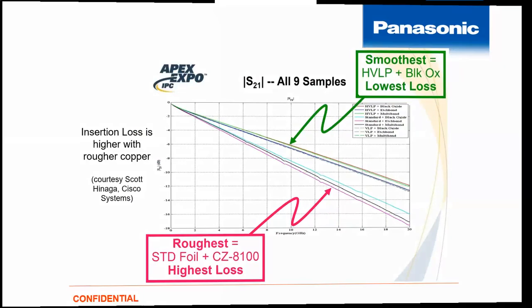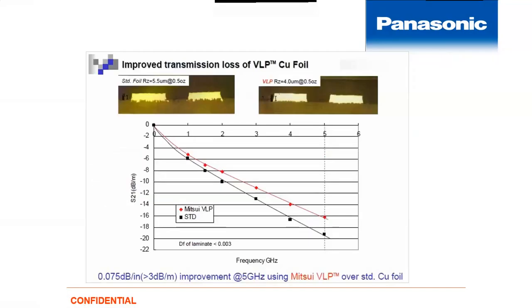If we look at just a comparison between standard foils and VLP, you get the point here again. The VLP performs better than the standard, and if you look at the cross section, of course, it's much rougher for the standard foils. Traditionally we were looking for better bonds with that, but now we need not only to have the bonds, but we have to have the smoother copper for the better electrical performance.